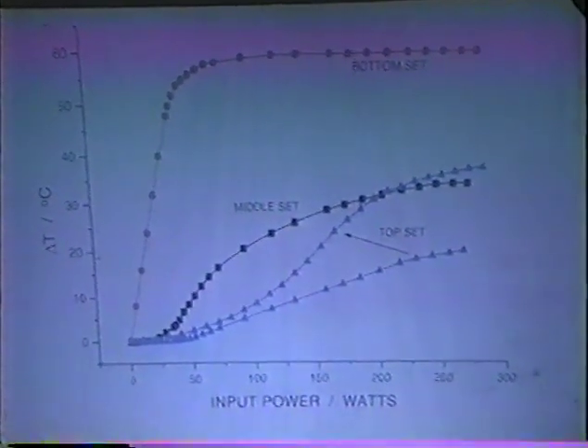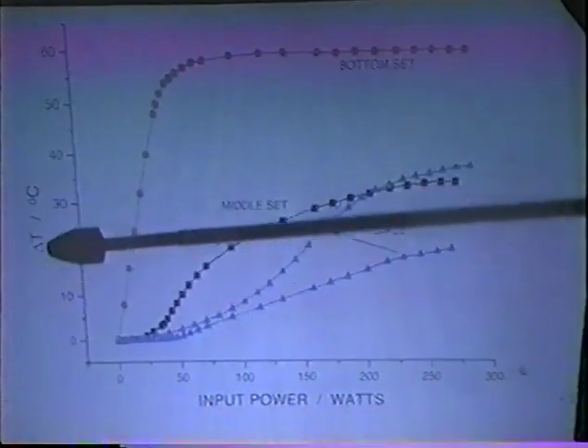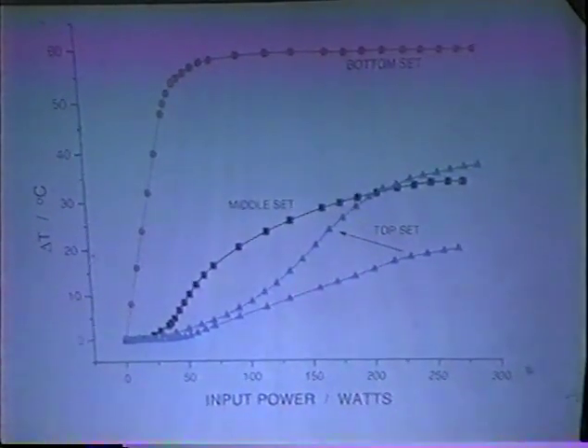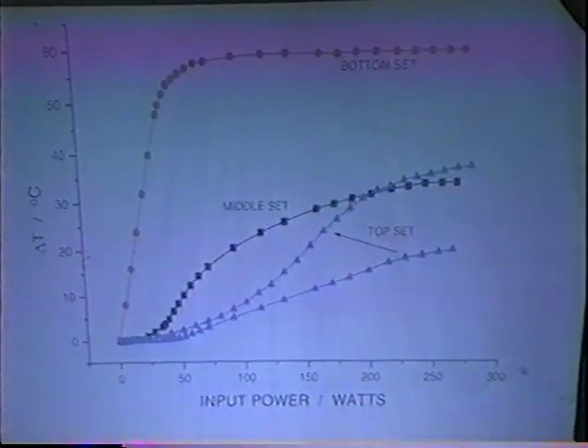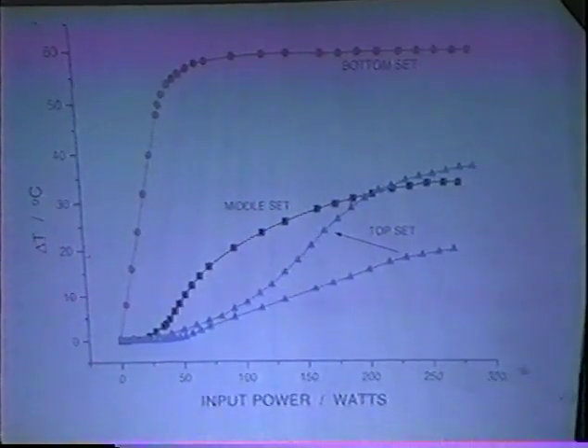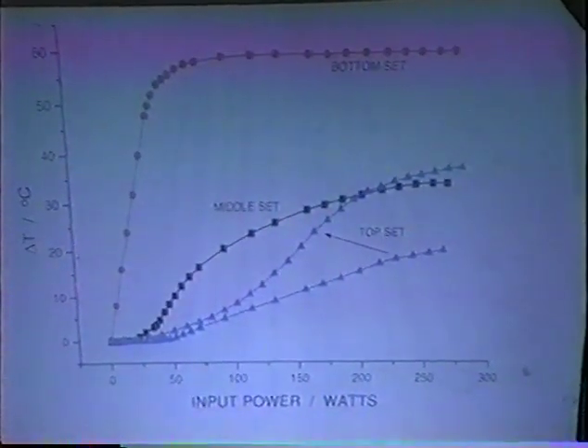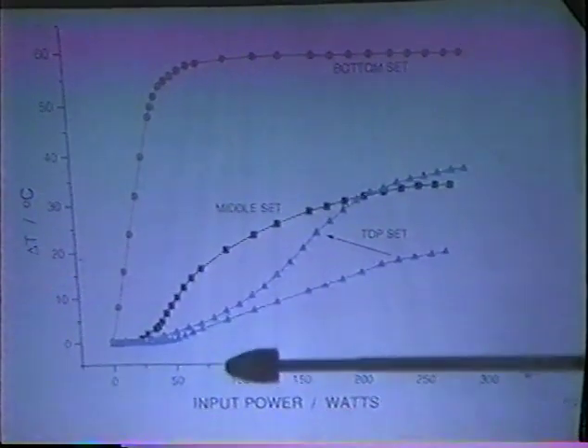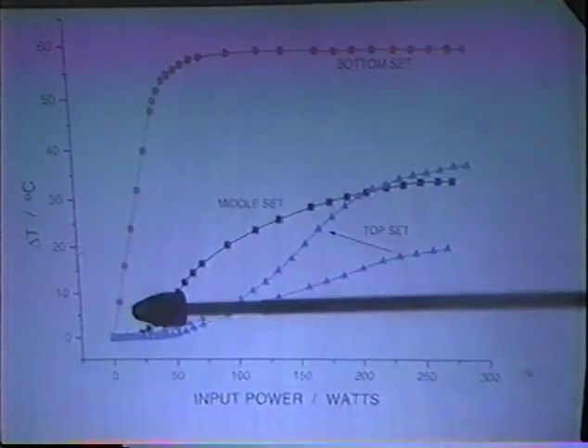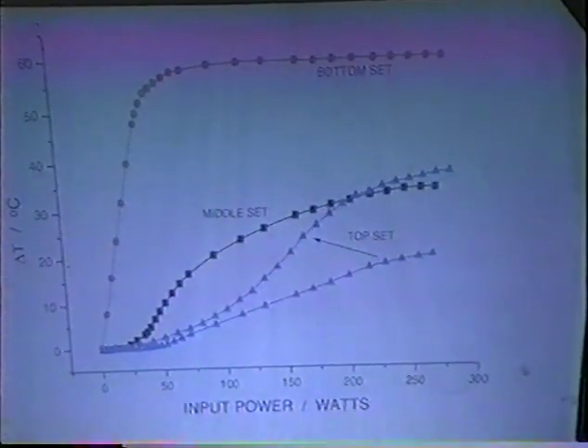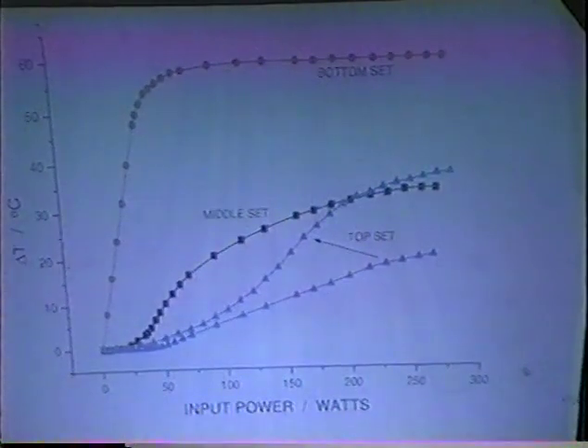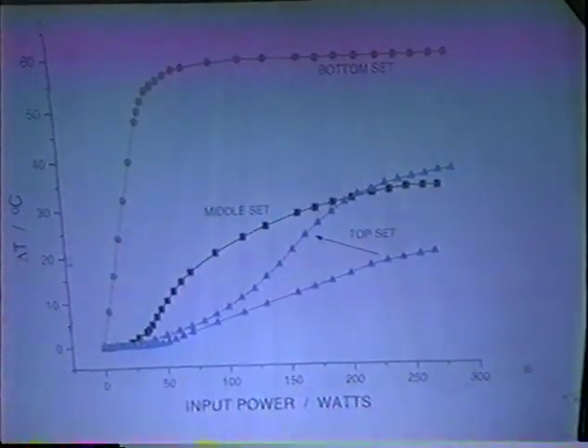No. Okay. This is the change in temperature that you measure, the difference in the inner compartment and the outer compartment of the cell as a function of the input power. This is the kind of calibration which you want to end up with. So you will know what your cell input powers are, and at each input power you would then calibrate by measuring the difference in temperature on the inside and outside of the cell. The principle itself being quite straightforward.